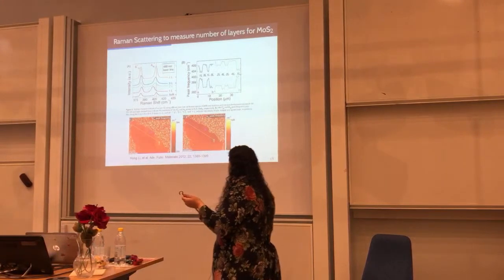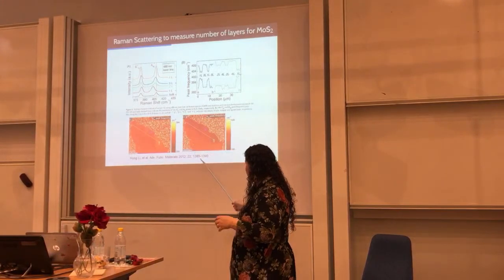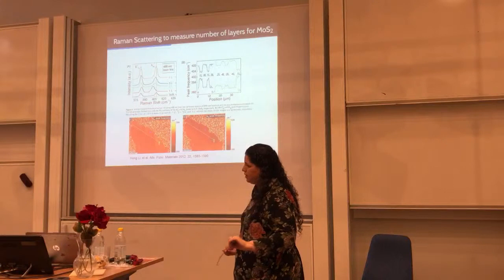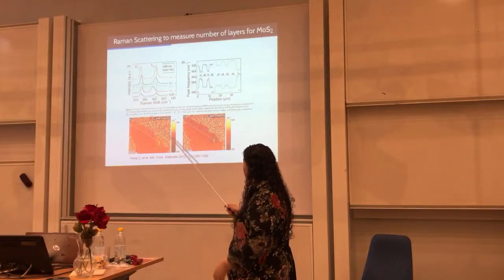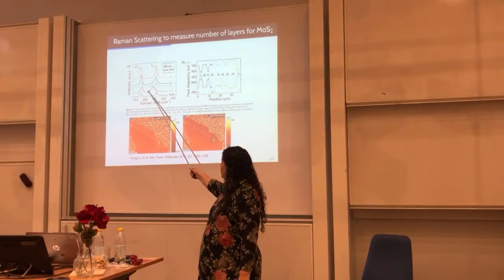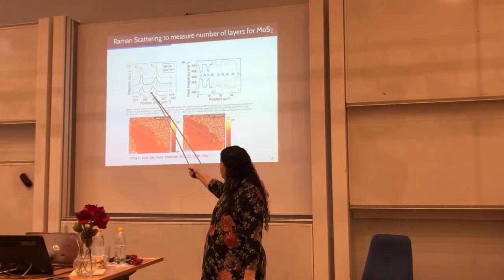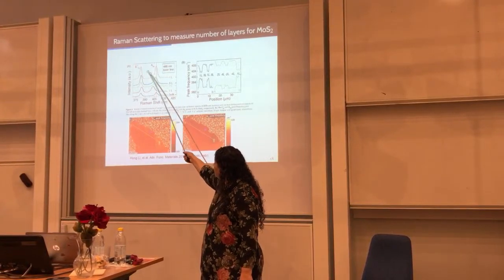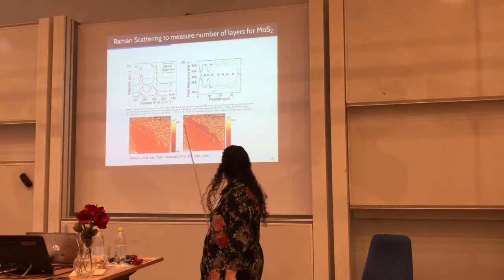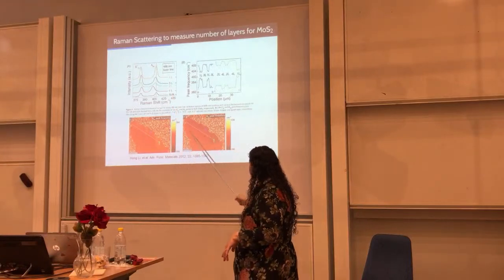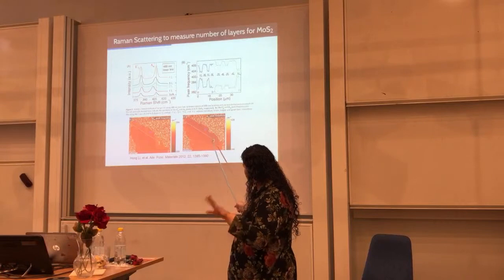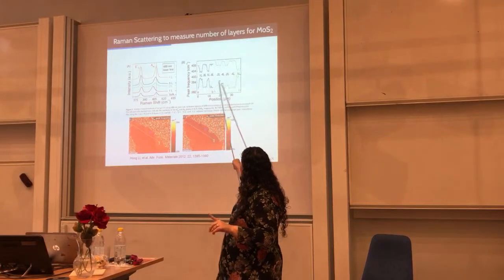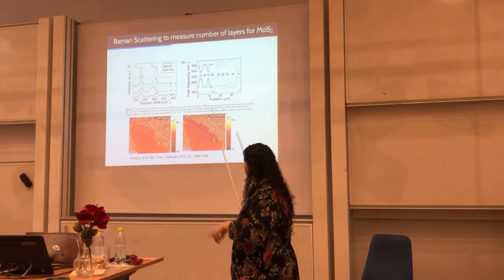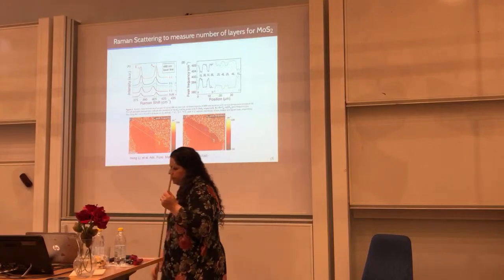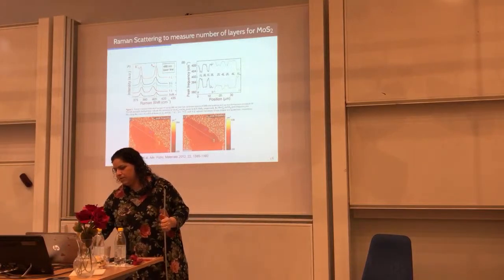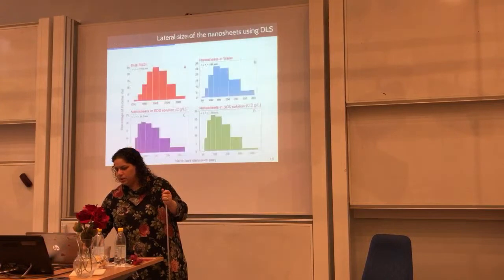So these are the results from the literature that I based my studies on to evaluate the number of layers. So you can see that for one layer, the position of the bands would be here, and four layers is more or less where we got our results. They did their experiments on silicon wafer as well, and you can see the shifts that they had, and how this paper is a reference for this kind of studies. Okay.